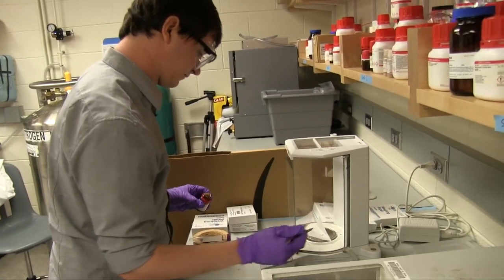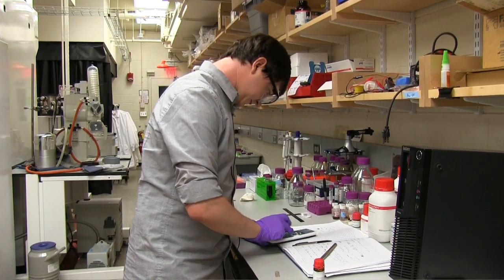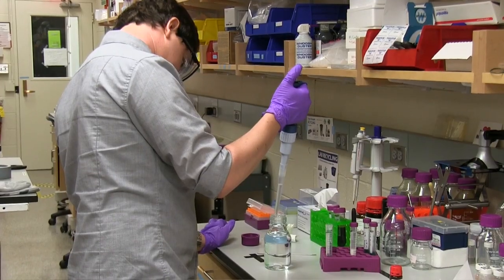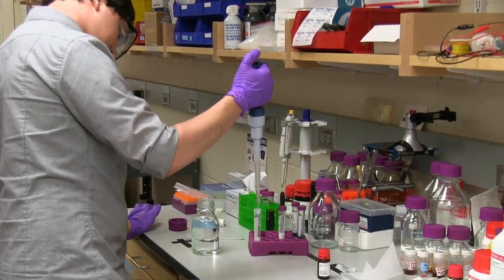We are really interested in how much metal we can add into our hydrogels. What we found is that we don't need to be at a very specific metal-ligand stoichiometry that a lot of people expect, and that as long as you're above some critical metal concentration, you can get a robust hydrogel.